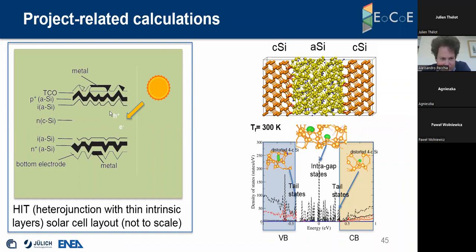In fact, we are dealing with the transport simulation of amorphous silicon, crystalline silicon. This is just a more complicated structure than the simplified tutorial, but here we have an amorphous object with a lot of hydrogen saturation and dangling bond defects. So trivalent, pentavalent silicon. And all of these defects give you peaks in the gap of the crystalline silicon material, let's say. So the main task of the EoCoE project was to compute them with ab initio accuracy, and then possibly set up this interface to do Wannierization of this and an interface to LibNEGF.